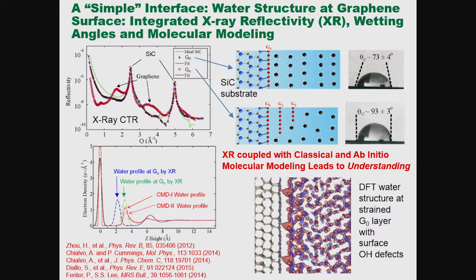There's always layering. So this is a plot, that's the surface, and these are dense layers of water molecules moving away from the surface, extending up to maybe 10 angstroms, or 10 water diameters, away from the surface. In order to understand these X-ray profiles, we hit this with computational modeling, using classical MD as well as ab initio approaches.